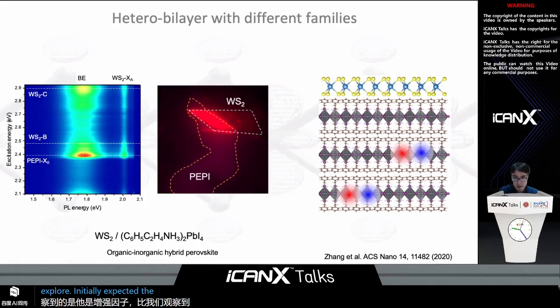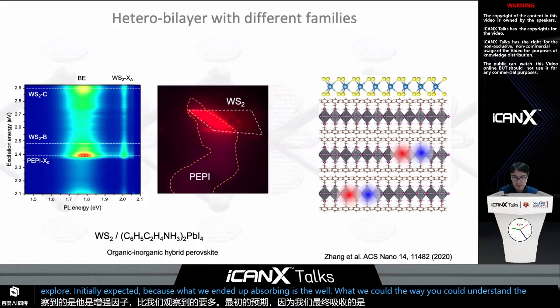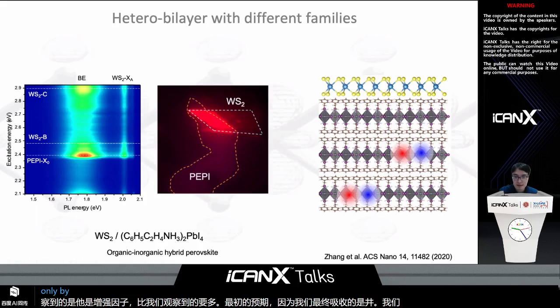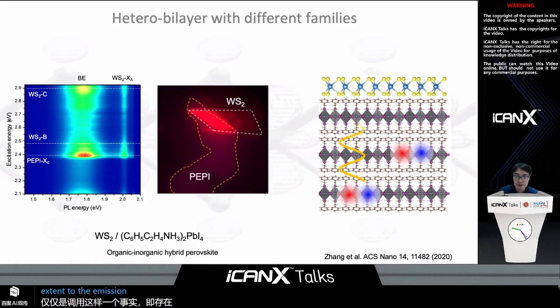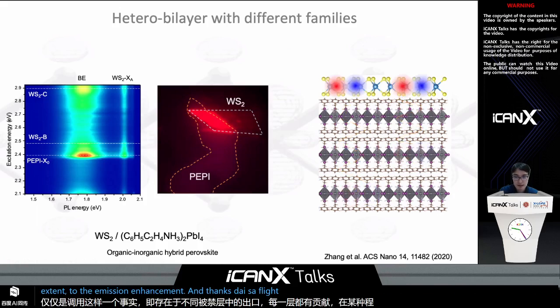because the way we could understand this data is only by invoking the fact that there are excitons living in different layers of perovskite, and each of those layers contribute to some extent to the emission enhancement in tungsten disulfide. Okay.